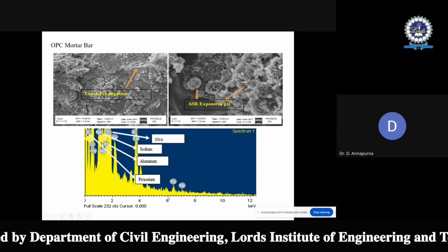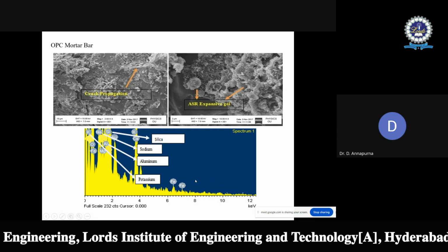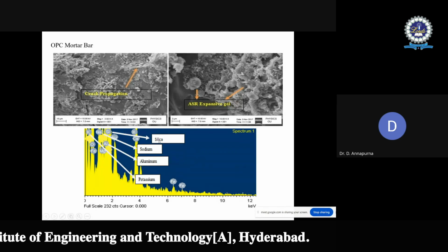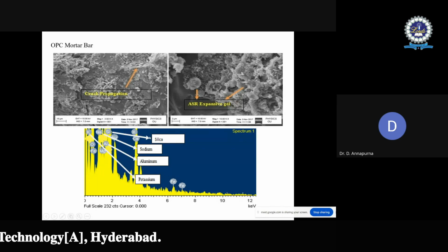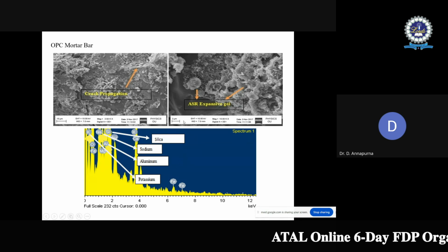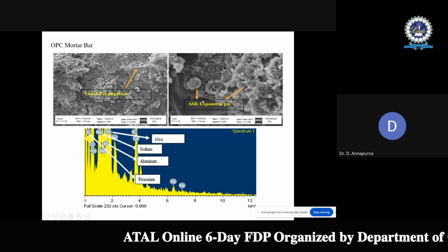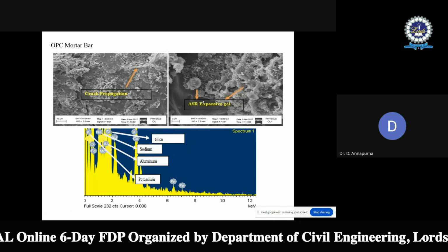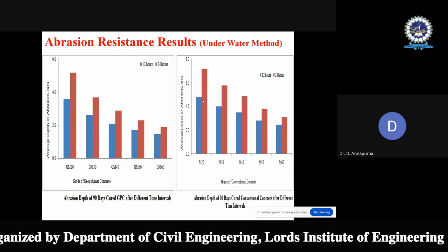And in the chemical compositions, higher traces of silica, sodium, and accumulation of potassium, aluminum, sodium silicate are confirming the presence of alkali silica reaction expansive gel. So this is about the alkali silica reaction.